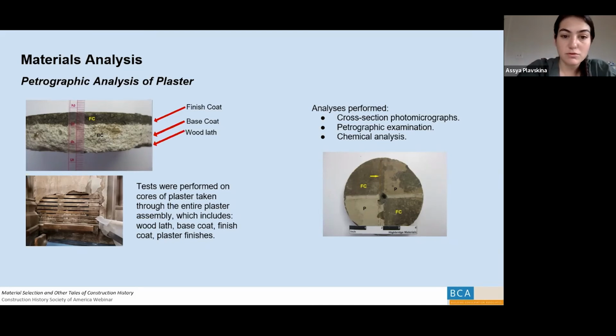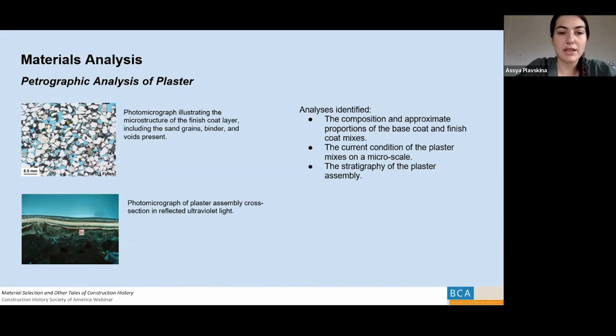In case those of you who don't know plaster stratigraphy, this is typical. The section that you see here is a pretty typical plaster installation, where a base coat, which in the top left photograph you see as the whitish gray, is applied over wood lath. And then above that is a finish coat, which you sort of see as the reddish brown. And then above that are our finishes layers. And we performed the analysis that you see on the right. The goal of these analyses was to understand the composition and proportions of both the base coat and finish coat, hoping that that information would provide us some idea of the construction timeline, and also understanding the composition would allow us to understand the current condition of the plaster on a microscale level.